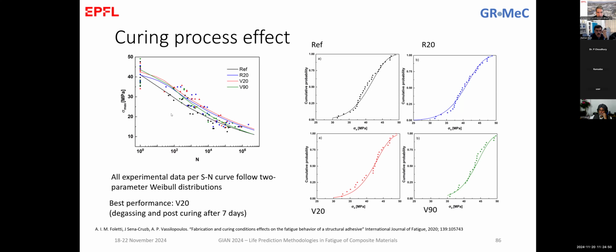And then if we go to compare the behavior, we can see that the reference samples are the lowest, showing the lowest fatigue performance. And this is attributed to the post-curing. You remember before I said that the specimens are continuously increasing their properties even up to a year. So for these reference specimens, we expect that if we test them again after a year, they will show performance relevant to the other lines, which correspond to specimens that have already been post-cured. So the post-curing helps.